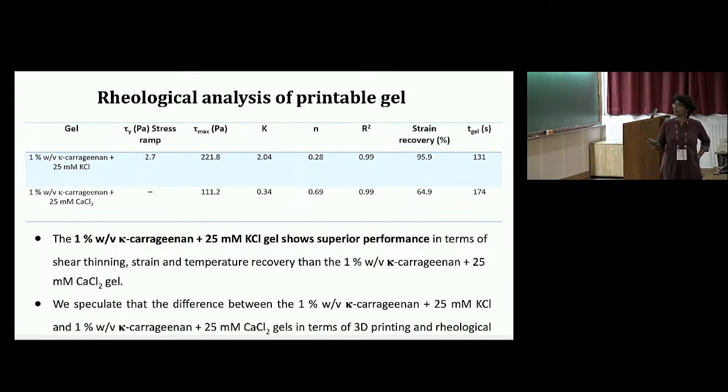The highlighted ink is our candidate for printing, which gave us the pore printability equal to 1, and all the structures. The non-highlighted one is the one which had the higher strength but could not print well. These are measured at 45 degrees Celsius, which is our printing temperature in the nozzle.